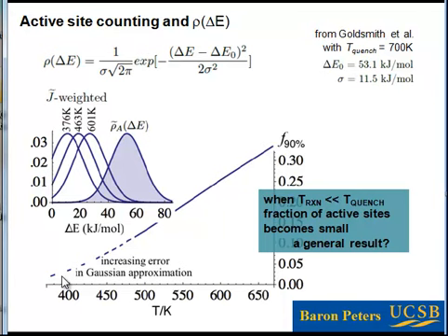And I think when you follow the arguments that led to this quantitative analysis, you realize that we should expect that when you synthesize a catalyst by some calcination process at very high temperatures, and then you rapidly quench that catalyst, you have frozen in a bunch of local geometries that are representative of a very high temperature. And then once you operate that catalyst at a lower temperature, those sites aren't going to change. And so you should expect that that broad distribution of different local site geometries is going to give rise to a phenomenon like this, probably in many cases, right?